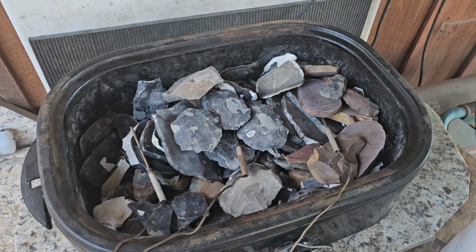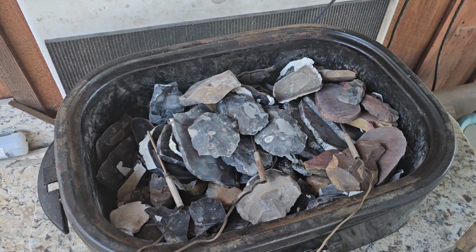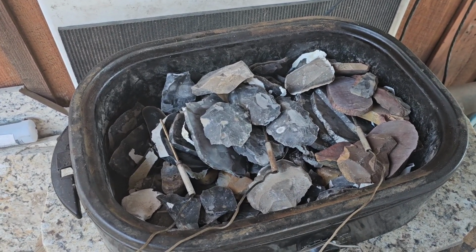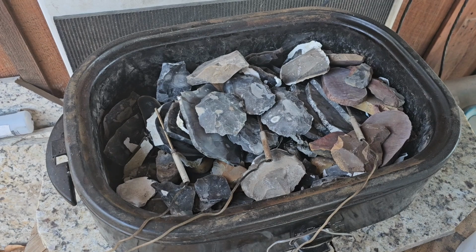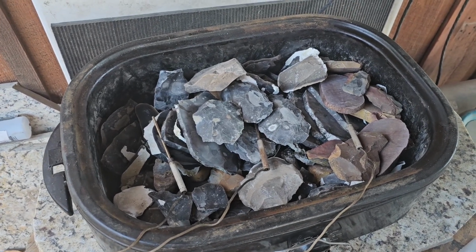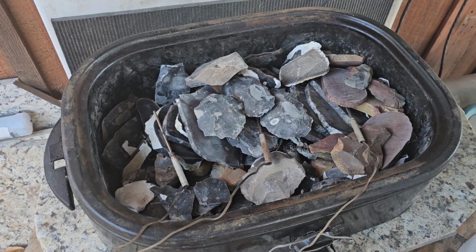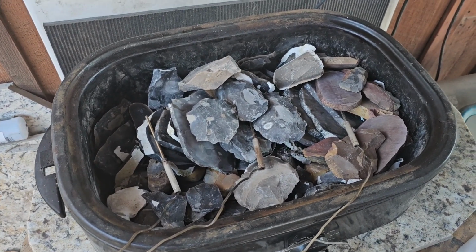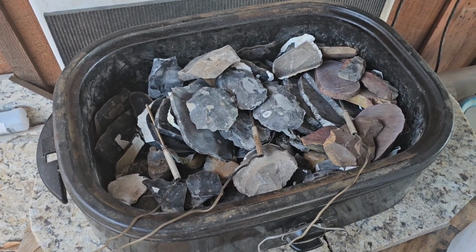And on this, after we go to 450 and the hold time, I'll probably hold that for 12 hours. And then I'll turn it down to like 350, let it sit there for a couple hours or so, then I'll turn it down about 50 degrees an hour or something like that. That's what I'll move it down. So I do move it down a little faster in the turkey roaster just because I don't have the same control. But okay, all right, and we'll pick it up when we go to check this.